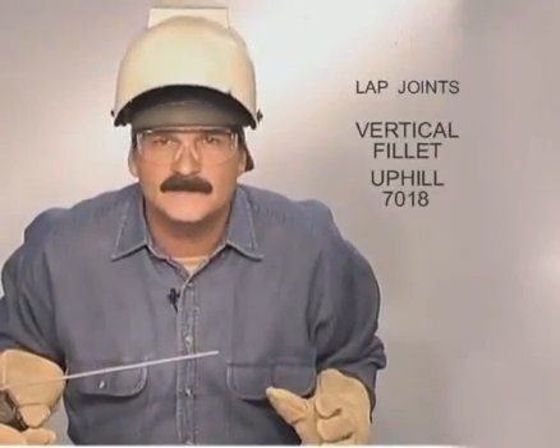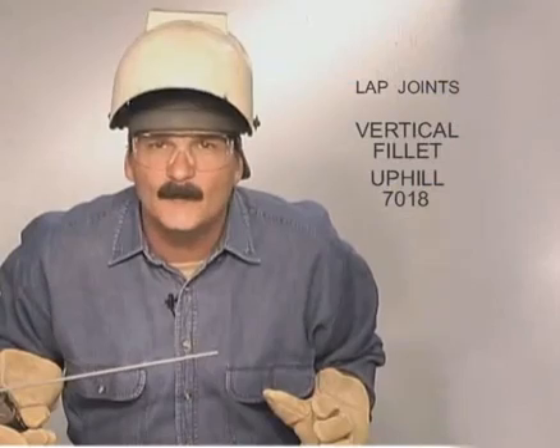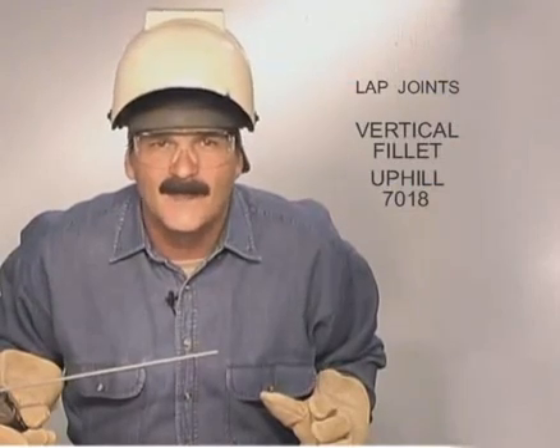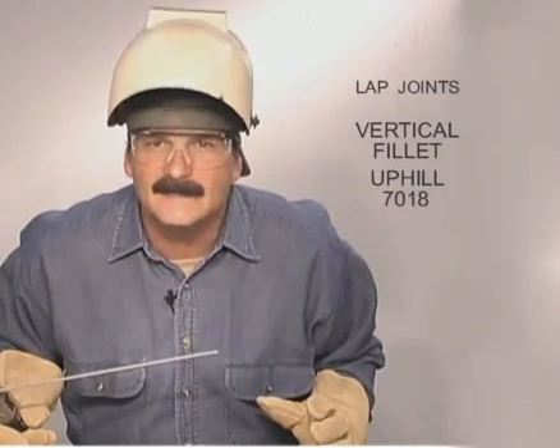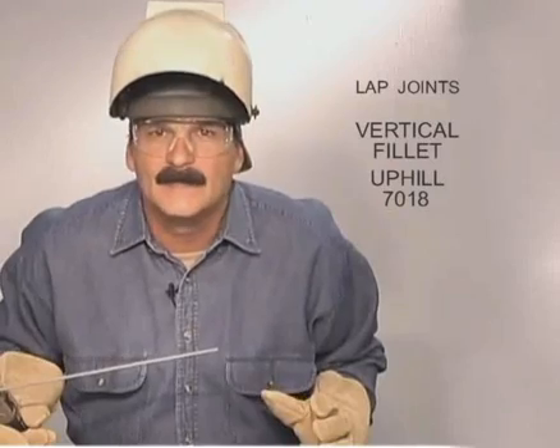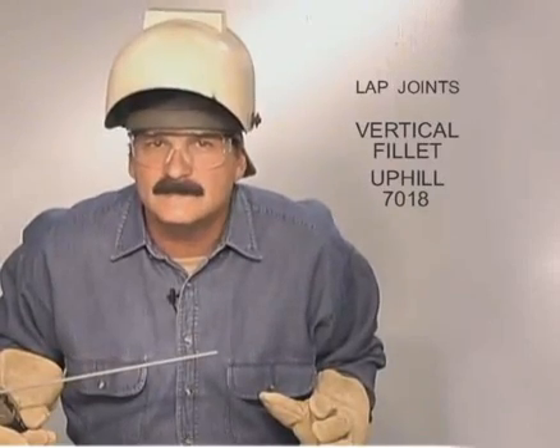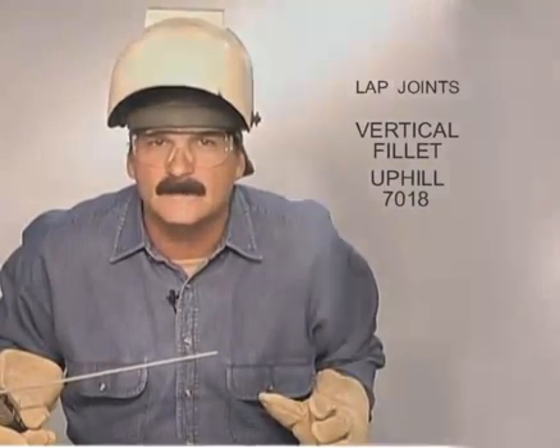You aren't going to build up a lot of weld on a vertical down, so you'll probably need to run a second pass. Vertical up with 70-18 will not only provide a stronger weld, you can also build up more filler metal in one pass. Always keep in mind that 70-18 is very sensitive to the arc gap. You don't want to jam the rods into the sides or long arc across the center.